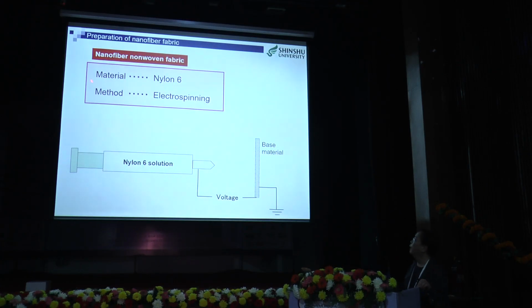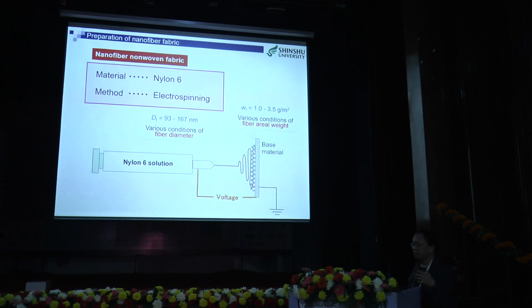In this study, we prepared the nanofiber non-woven fabric made of nylon 6 by electrospinning method in this way. The fiber diameter was variously adjusted by controlling the nylon 6 solution concentration. The fiber diameter is in the range of 93 to 167 nanometer. And the fiber area weight onto the base material was also variously adjusted like this.